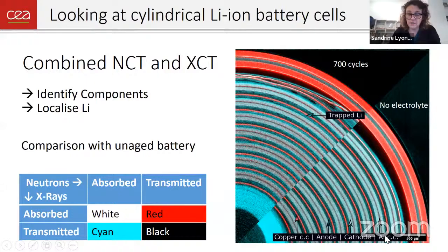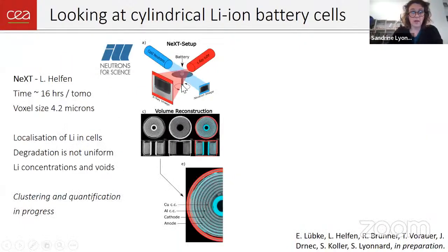So again, you can identify all the elements. You have your copper current collector that is in red, the anode, the silicon-based material that is double-side coated on this current collector, and then you have the separator, and then you have the second double-coated cathode on an aluminum collector. What you see when comparing the images, just a very raw observation, is the blurring of the image in an aged cell, and this is because you have some lithium that has been trapped a bit everywhere, and you also have some voids, regions that are depleted in lithium. And this is due to aging. This is exactly what we need to understand. So basically, we have first some ex situ experiments with neutrons that give us nice images.